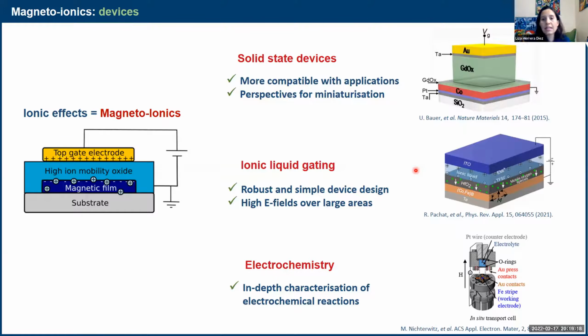Of course, this kind of electric field can be achieved with solid state devices, but you probably have to work quite a bit to get a nice device in the clean room that can do that. However, ionic liquid is the easiest thing you can imagine. You just put the ionic liquid on top of your surface, you stick a wire into it, and that's your device, and it works. So it's a very robust and simple way to apply an electric field and to study its effects. Also, you can do it over a very large area. So if you need a large area for a technique that has very little signal, for example, this is really the way to go.